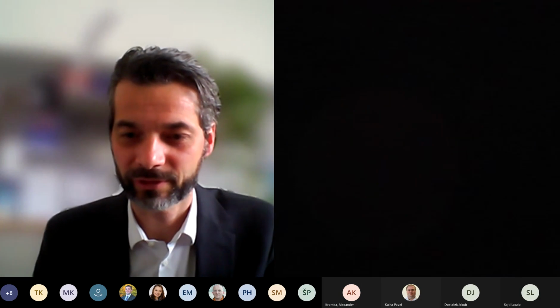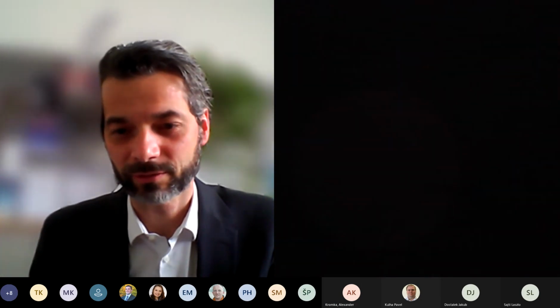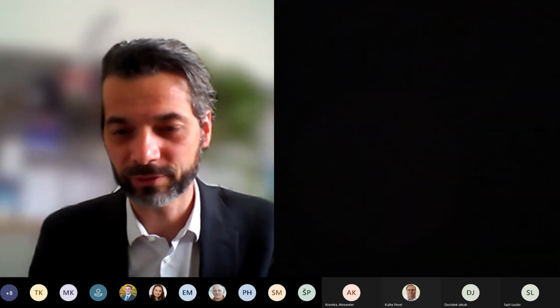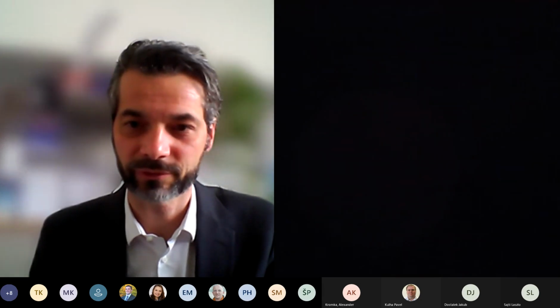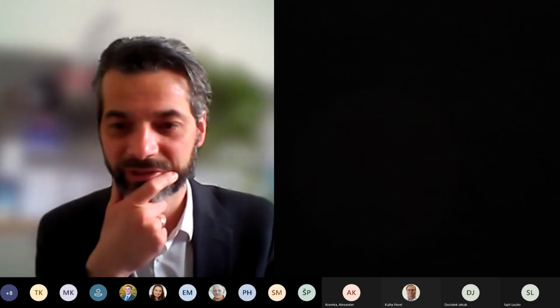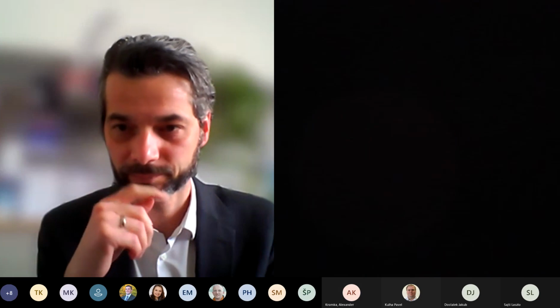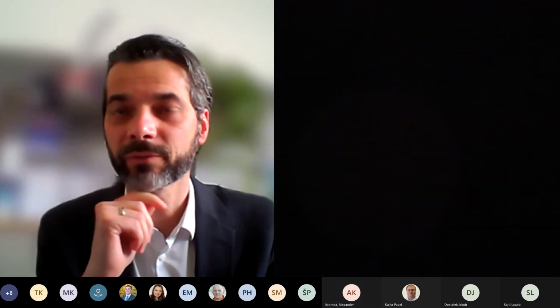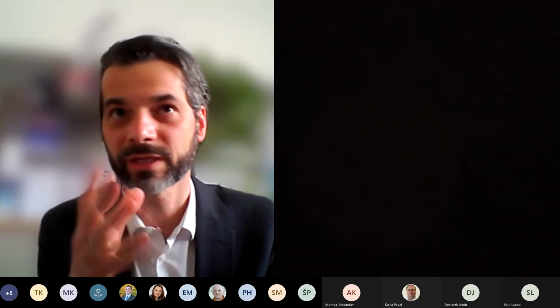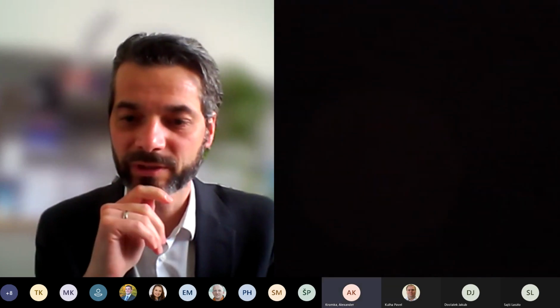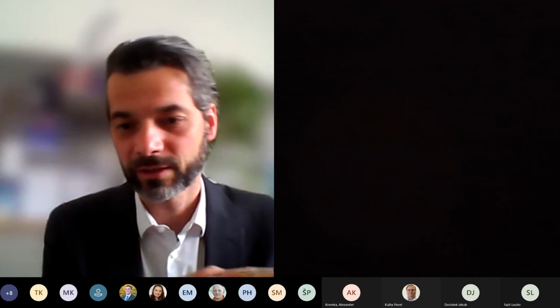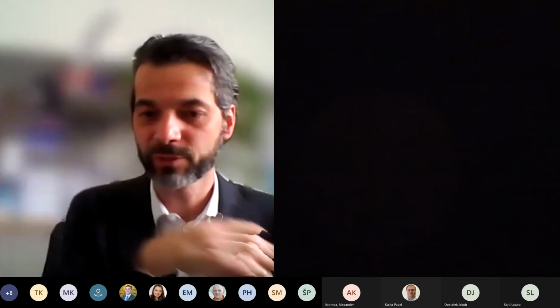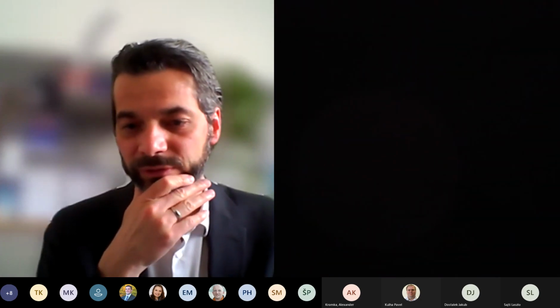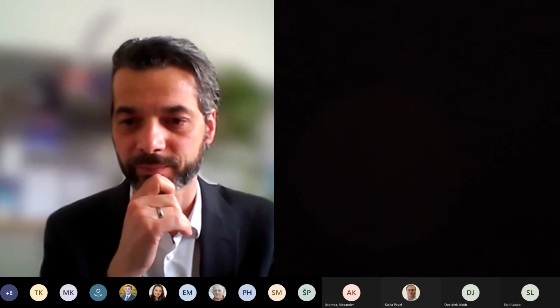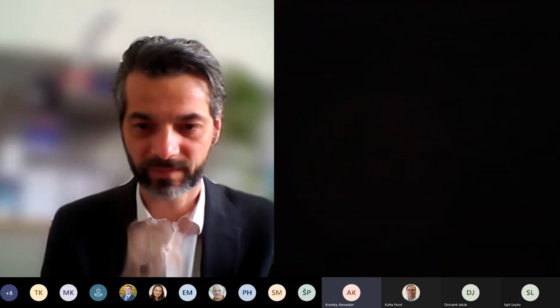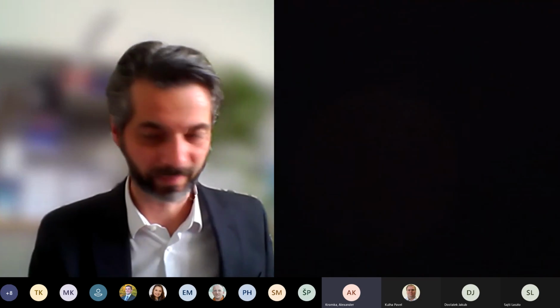Actually, we're also doing nanoimprint lithography on rough surfaces. This depends on the local curvature that you have and on the type of nanostructures you want to have on your surface. I don't have an image with me right now. I mean, we can maybe talk later more in detail. But for example, what we have done is imprint a grating structure, which was 200 nanometers high at a few hundred nanometers in period, on top of a diffuser structure, which is several tens of micrometers in height, but with a very smooth surface. So this is possible, but it would have to be looked into for each application. Thanks. I will contact Pavel Kulha and we will discuss details. Thank you.